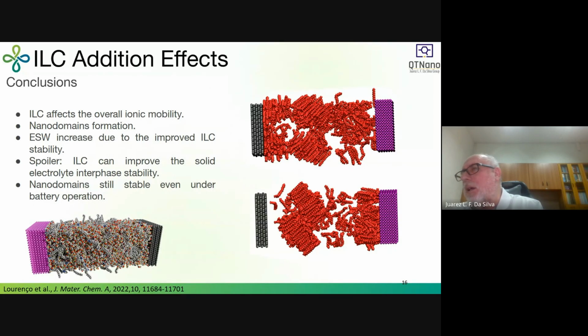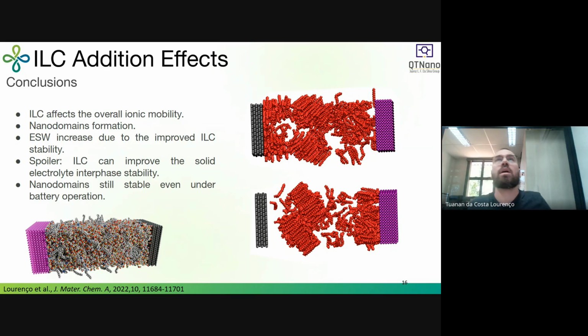Can you comment on the liquid and solid electrolytes in sodium-ion batteries with respect to ionic conductivity, stability, and safety? Okay, so for solid electrolytes, we have different classes, like polymer solid electrolytes, but also inorganic solid electrolytes. In general, when we go from liquid to solid electrolytes, we see an increase in the safety of the battery because if you have a solid electrolyte, there is no leak effect, so you decrease a lot the problems regarding safety. Also, in general, solid electrolytes have lower toxicity and lower flammability, and of course, the vapor pressure is not a problem anymore. However, the problem inside the solid electrolytes is first the ionic conductivity.